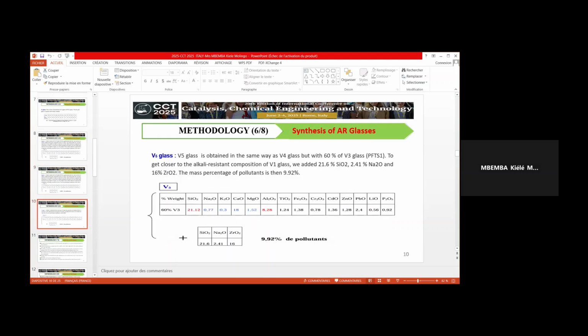The V5 glass is obtained in the same way as V4 glass, but with 60% of V3 glass. To get closer to the V1 glass composition, we added 21.6% of silicon oxide, 2.41% of sodium oxide, and 16% of zirconium oxide. The mass percent of pollutant is then 9.92%.